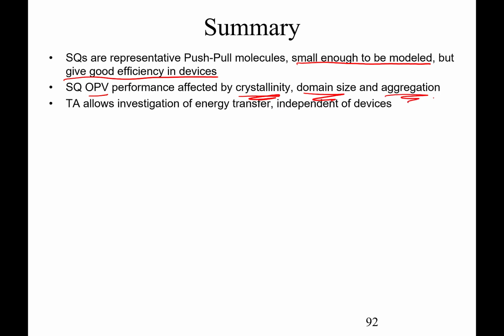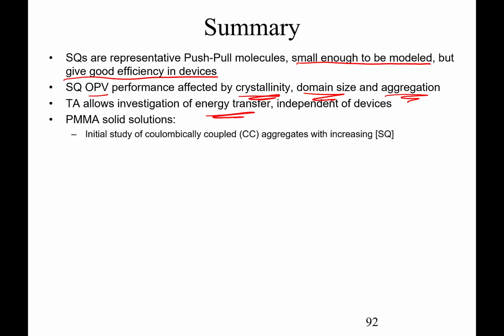Transient absorption is great because it allows us to look at energy transfer independent of devices. These polymethyl methacrylate solid solutions are fantastic to work with. They can give us this initial study of these coulombically coupled aggregates, these dipole-dipole interactions, on molecules that are fairly well separated. We are also looking at intermolecular charge transfer aggregates in films using transient absorption.